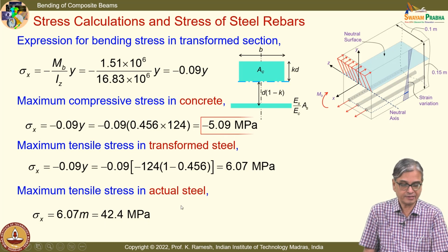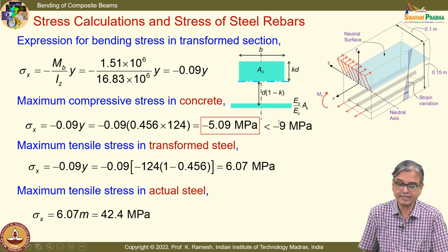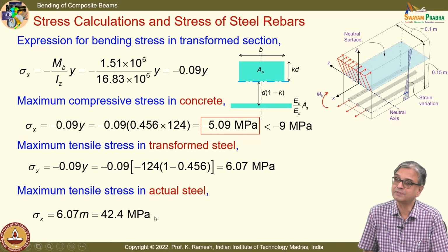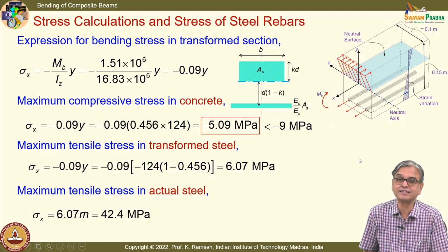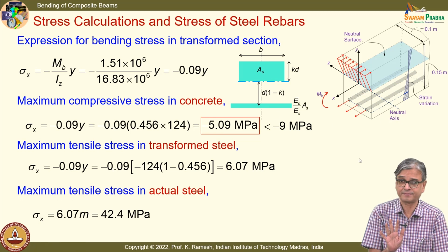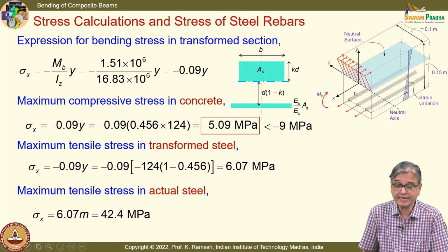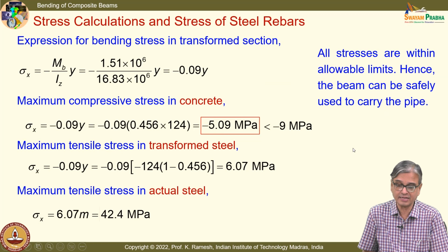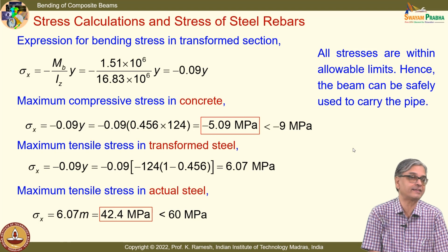And if you look at your basic requirement, concrete should withstand only 9 MPa, and steel about 60 MPa. I have got these numbers very close, and these two figures summarize what happens in the cross section. It is a very interesting problem, fine. And the key point here is the steel bars are perfectly embedded. So, all stresses are within the allowable limits. Hence, the beam can be safely used to carry the pipe.